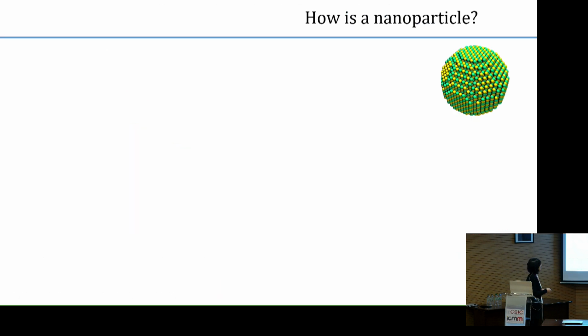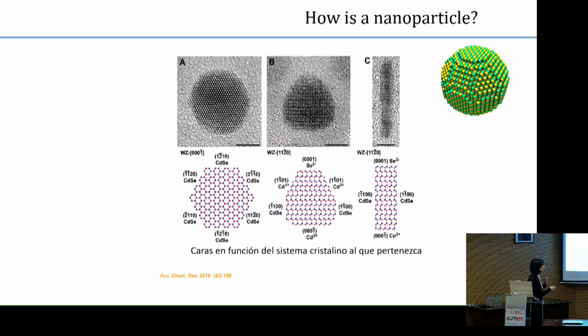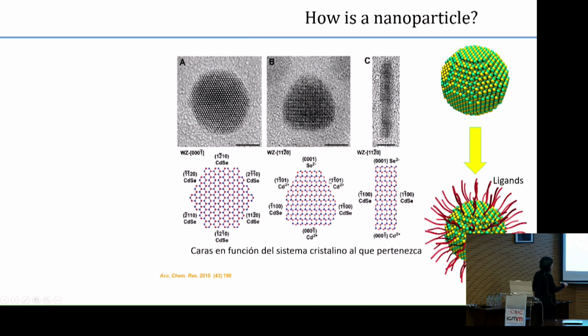Okay, but how is a particle? A particle indeed is not like this. We have seen in the TEM images that we have very nice particles where we can distinguish the crystallographic facets. But indeed, the particle is not like this, but it's like this. So it's covered and passivated with organic ligands that provide the colloidal stability in solution. Otherwise, they would all be flocculated.